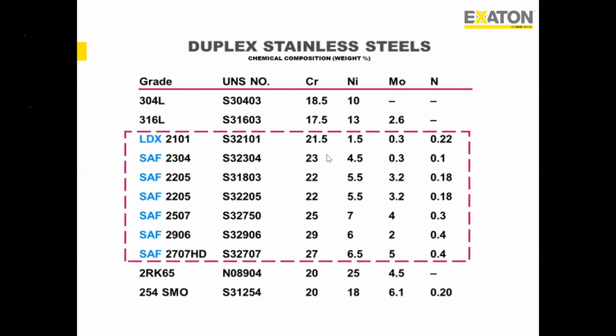So if you see here, from lean duplex to super duplex and hyper duplex, most of the alloy elements are basically increasing. There's a significant increase in chromium content: 22, 25, 27, or 29. There's an increase in nickel content from 4.5 to 5.5 to 7, hyperduplexes 6.5. Molybdenum content from 0.3 to 3.2, 4, and then 5.